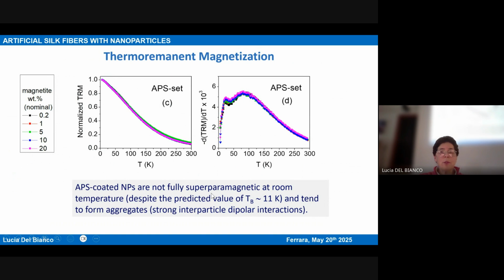And this is strange, because the predicted value of the blocking temperature for this small nanoparticle, the size was less than 10 nanometer, was around 10 Kelvin. And if you calculate the derivative, of course, again, you have all the curves superposed, but the maximum is at much higher temperature, one order of magnitude larger. And this is a clear indication that your nanoparticles are aggregates. And therefore, they feel very strong dipolar interaction. And so one can conclude that this type of nanoparticle with this coating is not good to be dispersed in the solution. And what happens most likely is that the nanoparticles precipitate when put in the starting aqueous solution, and therefore some magnetite was lost since the beginning and did not enter into the fiber.